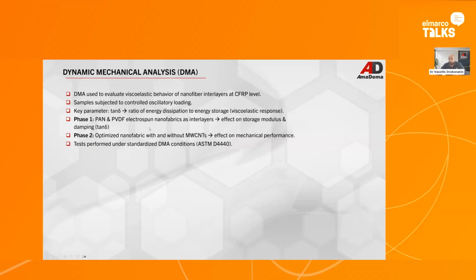Samples are subjected to controlled oscillatory loading. Key parameters are the tan delta as well as the energy storage. And then we have phase one, where PAN and PVDF nanofibers as interlayers are examined, seeing the effect on storage modulus and damping, the tan delta, and then optimizing the nanofibers with and without the carbon nanotubes, and the effect on mechanical performance.